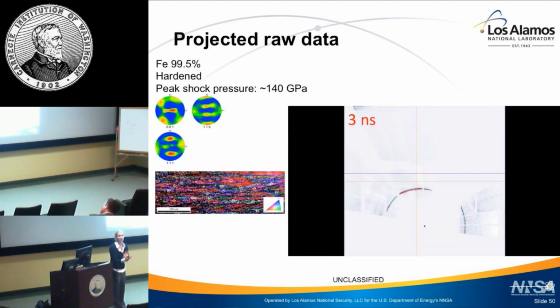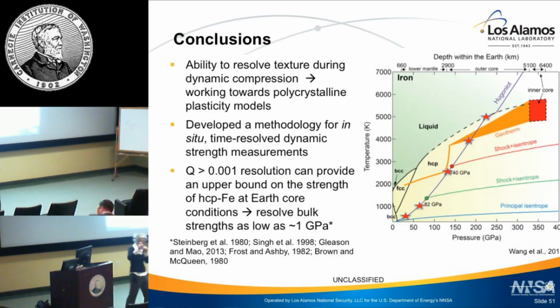Not all the way up to 3 megabar, but we can follow along the Hugoniot up to that melt bound, and then on release as we look at melt and then resolidification. And the resolution is appropriate to actually make this measurement. So that's very exciting. So to conclude, in the final seconds, we've sort of taken a tour through the Earth,